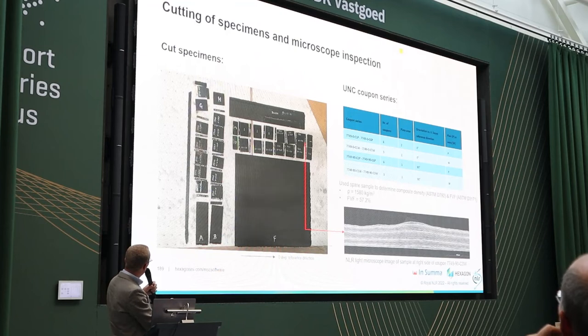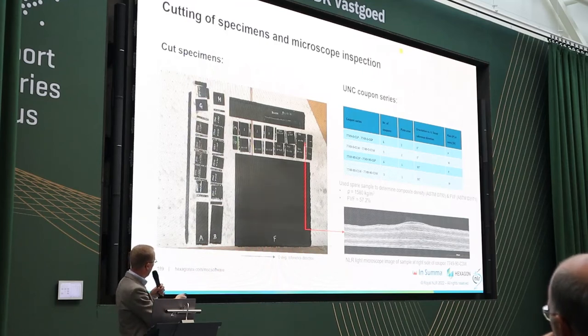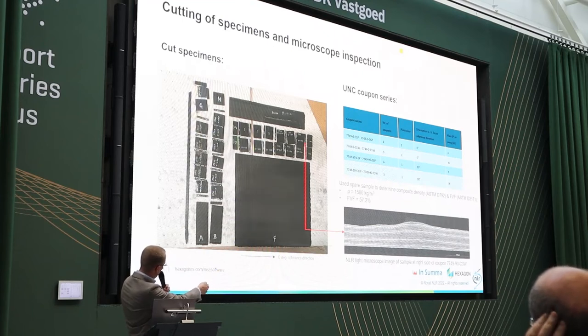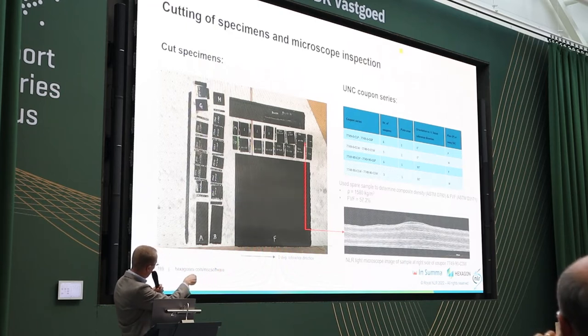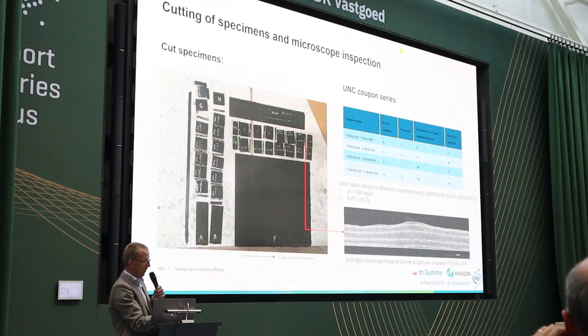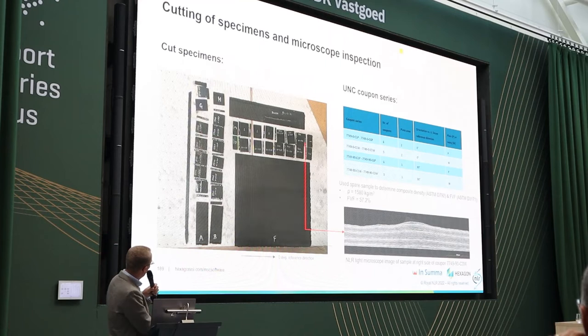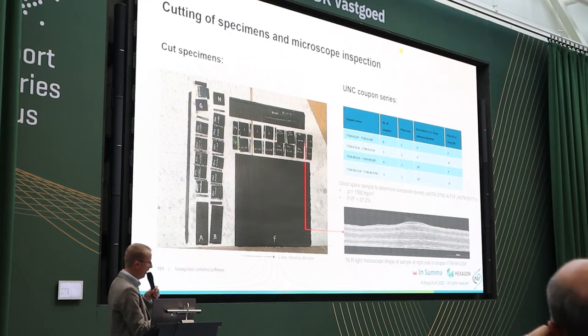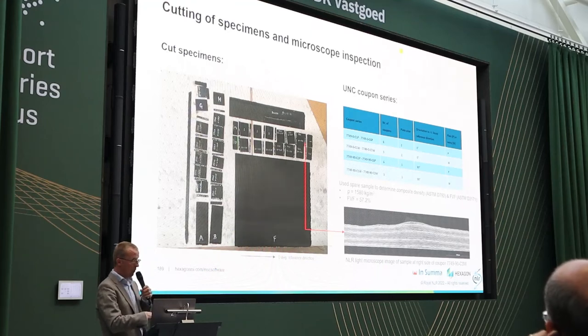In the left picture, you see the unnotched compression coupons that I cut from the plate, and also some small specimens that are mainly used for light microscope research. On the right bottom, you see one of those images made by the microscope, and you see clearly the out-of-plane fiber waviness. The most gray areas are the 0 degree plies, and the other fibers are coming towards you or in the 45 degrees direction. In total, I had 20 coupons, and also did some testing with some spare specimens to determine the composite density and fiber volume fraction, which I can use in Digimat as an input parameter.